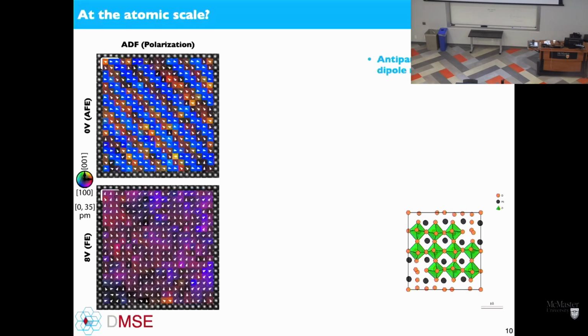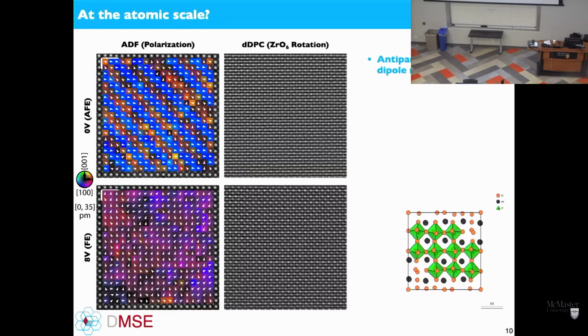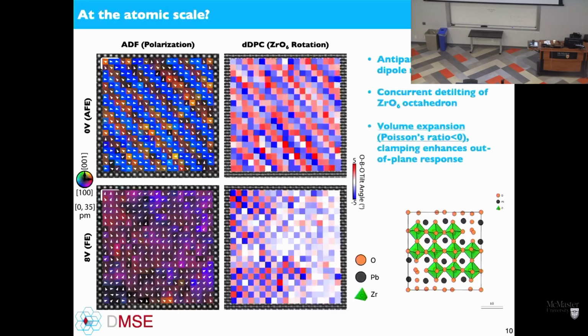And so we can measure the polarization and find that we have this antipolar nature. Again, antiferroelectric polarization cancels out. At 8 volts, we get polarization alignment along the direction. Now, conventional DPC or integrated differential phase contrast provides some information, but it's very difficult to really map out where all those atoms are at.